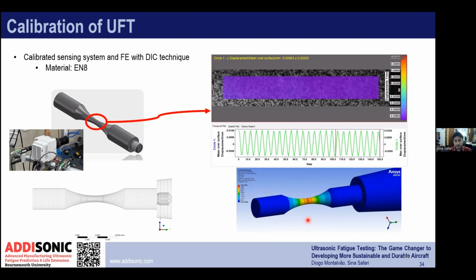So it shows the strain, for example, in the middle of the specimen using simulation, and what we are observing in the experiment using the DIC system, and the wave down there, the cyclic motion down there, shows us the strain in the middle section. So this is how we use the simulation and experimental data to calibrate, to make sure the machine is working as designed, and also to calibrate the FE model based on what we are observing in the experiment for later stages. So if we move on to the next slide.